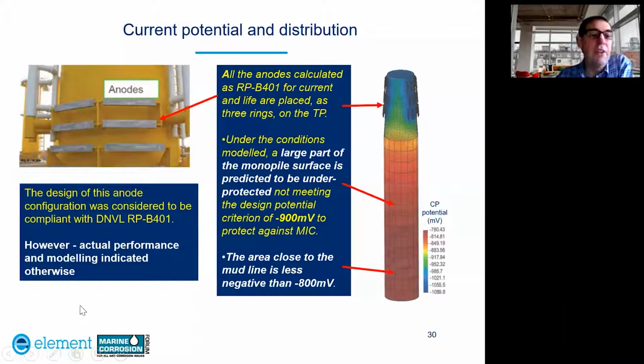So the design of this anode configuration shown here was considered to be compliant with the DNV recommended practice B401. However, actual performance and modelling indicated otherwise. So all of the anodes calculated as RP B401 for current and life are placed as 3 rings on the transition piece shown here, and also shown here on the model.